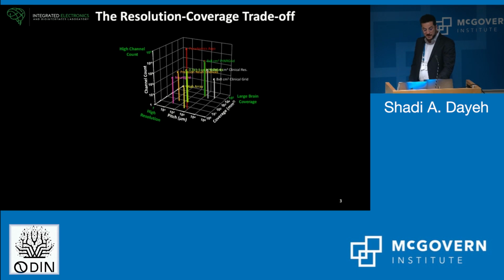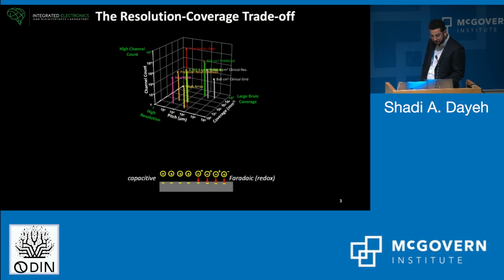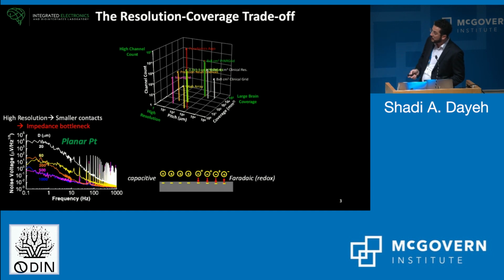So briefly, what are these fundamental technological challenges? If we want to stack a large number of contacts to measure brain activity, we would like to scale down the electrodes. Planar electrodes have a low number of adsorption sites to have electrochemical interactions with the brain, and therefore random processes become very effective at small dimensions. This shows in the noise of these electrodes. Here we're looking at the noise as a function of frequency for different diameters, and as the diameter scales from 1 millimeter to 20 microns, the 1/f noise scales as 1/D squared.